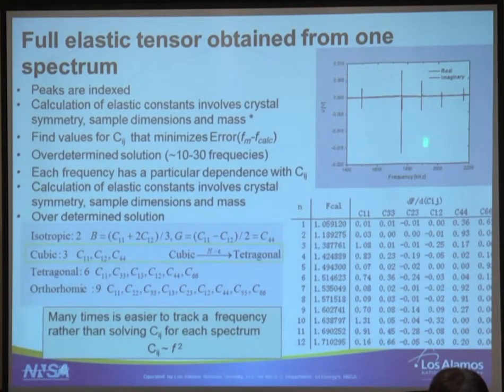So this is how we do it. We use a program that needs basically your geometry and your symmetry. This is very important. It's not the same to solve the elastic problem of a polycrystal, where you have 2 elastic constants, than to solve it in, say, an orthorhombic, where you have 9. In this case, in zero field, we have a cubic system with 3 elastic constants for MnSi, and then when we apply a magnetic field, we break it into a tetragonal symmetry.